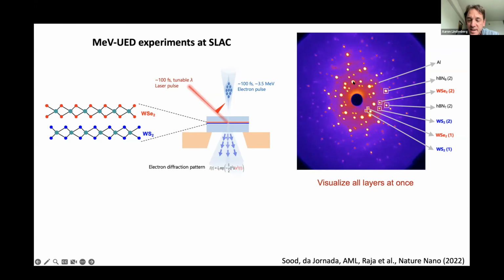Every spot here is a diffraction spot, but what we're measuring in this transmission mode is the superposition of the diffraction patterns from all of the layers in these samples: from the single WSe2 layer, from the WS2, from the hexagonal boron nitride. We can identify each one of these. And if you zoom in on one of these Bragg peaks, the power of this approach is that it allows you to really separate out the contributions from each layer.